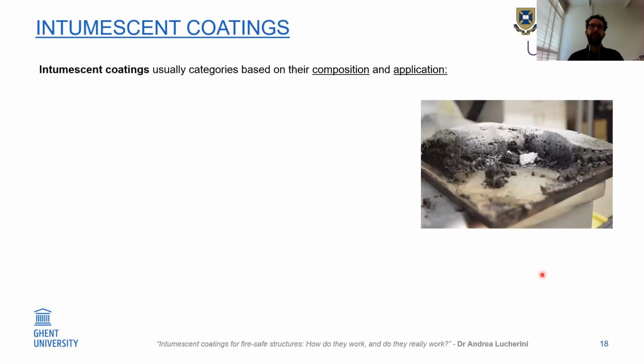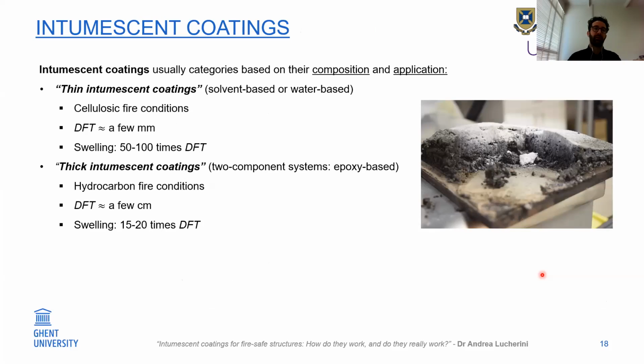So what is important to underline is that usually intumescent coatings are categorized based on their composition and application, particularly in two different categories. The first one is thin intumescent coatings, that usually are solvent or water-based, and they're usually prescribed in the built environment for cellulosic fire conditions, so for the standard fire resistance curve. They're usually applied at a DFT in terms of a few millimeters, and their swelling can lead to a swell char that can go up to 100 times the initial DFT. So if we apply 1 millimeter of DFT, we can get up to 10 centimeters of swelled intumescent coating.